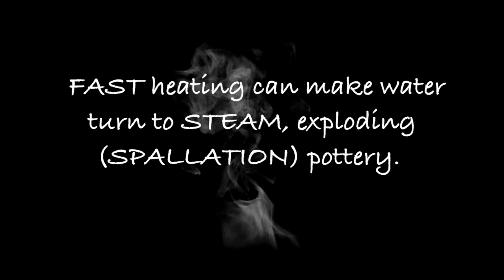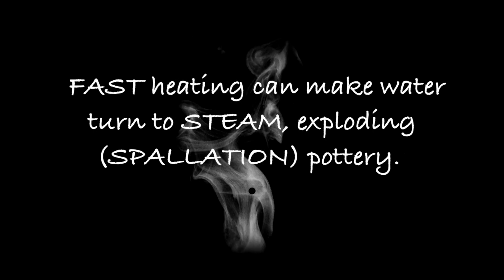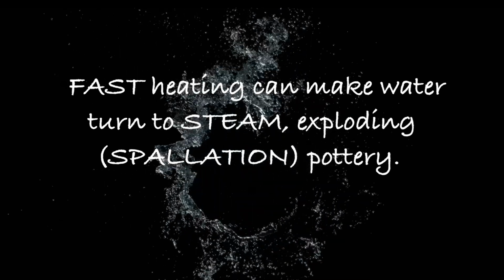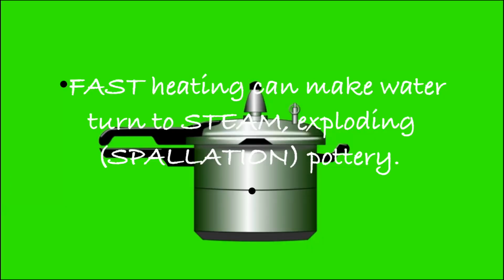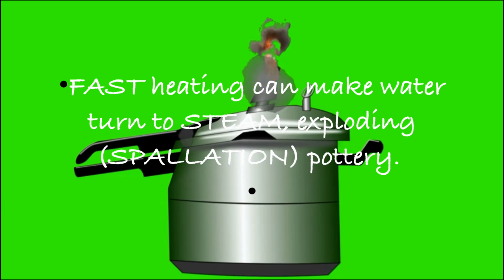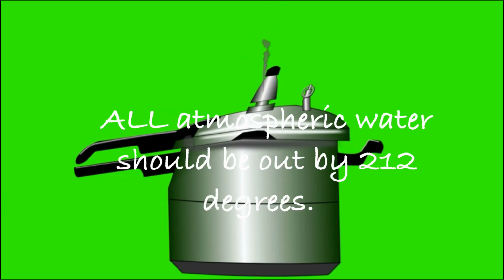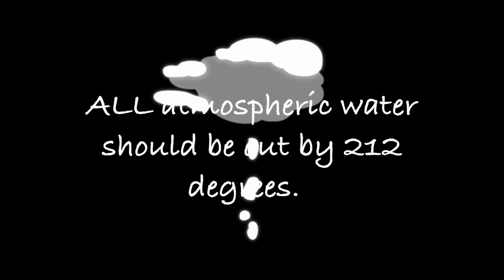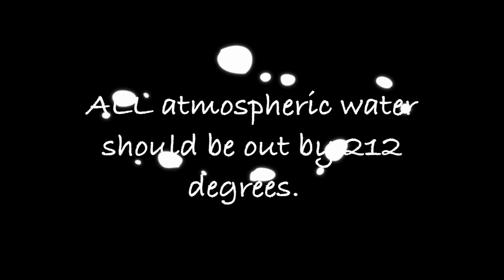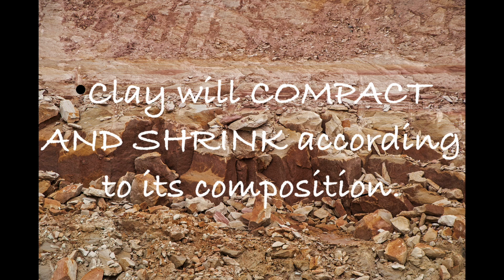But if heated too quickly, water can turn to steam, which explodes the clay in something called spallation. Think of an exploding pressure cooker or something like that. Make sure that you dry your piece as much as possible, because at 212 degrees, where water boils, all the water needs to be out of the piece. Clay will then compact and shrink according to its composition. Some clays compact and shrink more than others.